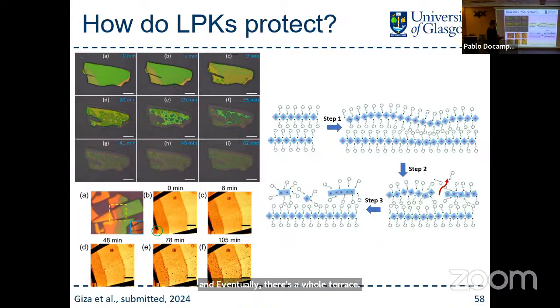So our proposed mechanism is that under exposure to humidity, the structure does buckle, and wherever you've got a defect, you lose one of the cations, that grows now laterally, losing all the cations in that row, ending up with lead iodide. The thing is, that lead iodide you end up with is now insoluble, and it's kind of like tiles. It's like the roof tiles. They're just layering on top of the perovskite underneath. So you don't have the same material you started with, but you end up putting something on top that is more stable. So it does work. It's just not what you think it was when we started doing this, which was a surprise to us. I'm not gonna lie. But anyway, there you have it. That did work quite nicely.